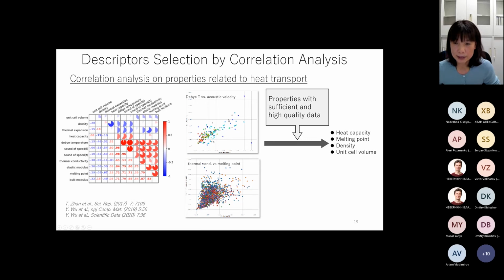If we plot them together, we can see a very clear linear relationship. And some others, like thermal conductivity and the melting point, have some weaker but still obvious correlation. And actually, if two properties have strong correlations, that means the physical and chemical factors dominating them are quite similar. So as a descriptor, we don't need to use both of them. We think we can just choose one, and it can be a representative of them.